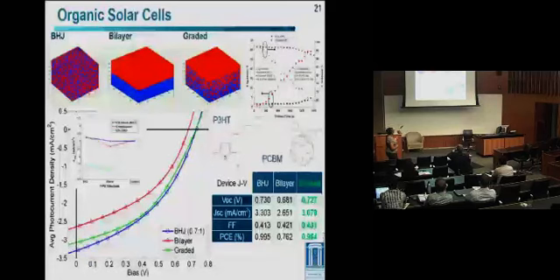We've actually grown these and characterized them, and we've confirmed that we do have a gradient in the composition from the surface by doing argon sputtering in XPS measurements. We've also done some Monte Carlo simulations to try to predict what our devices should be based on the material structure. From the simulation, we expect that the graded structure should have a much higher power conversion efficiency compared to the other two. Our model itself, in this case, is lower than the measured devices, but that's because of the unit cell size we used in the simulation. But the main point is that this gradient gives us better performance. And so getting better control over the gradient, I think, is a unique avenue to improving organic solar cell performance that's provided by the MAPLE deposition technique.